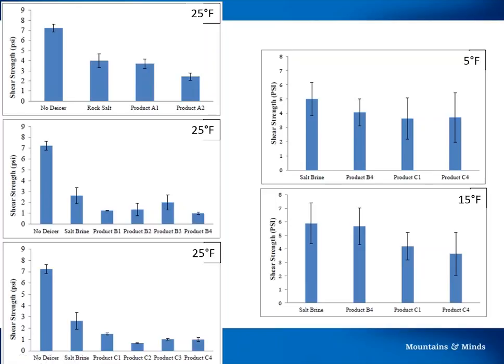As previously mentioned, a subset of the samples was then used for additional testing to try and tease out some of the mechanisms behind what was going on and why these products work. So salt brine was used as a control, and then products B4, C1, and C4 were used. The ice melting test was conducted for these products as well, as you may remember, at 5 degrees. So basically at 5 degrees and 15 degrees Fahrenheit, you can see here the difference in the shear strength required. What's interesting here is that at 5 degrees, for some of these products, less shear strength was required to remove the product. But also note these whisker marks, these black error bars, that's the variation between all the different samples that were run.